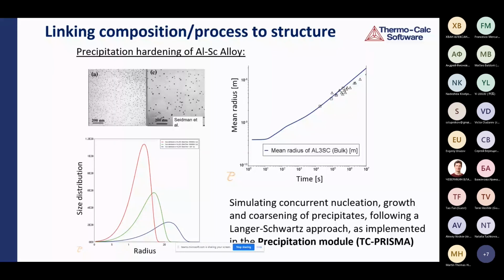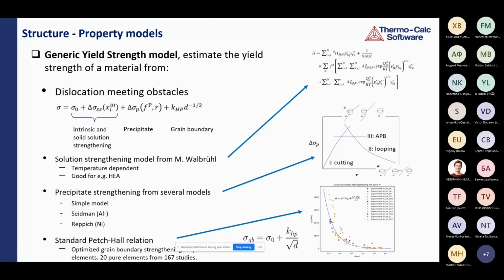And the generic strength model we have in Thermo-Calc today is actually a contribution of 3 different parts. We have solution strengthening models, the precipitate strengthening from several models, and the standard Hall-Petch relations. So all these in combination will generate the yield strength of the material. So back to this example.